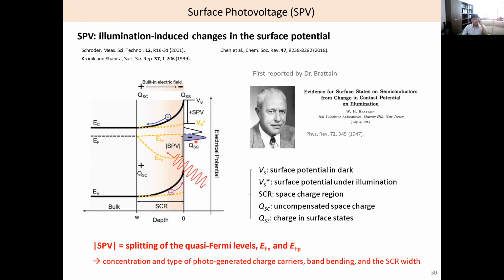Okay. Then we draw the Fermi level of electrons like this here. But what about when we now illuminate light? Light excites electrons from the valence band to the conduction band. So here, maybe you haven't seen this kind of notation. This is the transient electron Fermi level, and this is the transient hole Fermi level. Because we have more electrons and more holes, the electron Fermi level is a little bit higher. So this band is flattened a little bit. And this shorter distance means we have more electrons, right? By this light illumination. And then with more holes, we have this hole Fermi level. And these electrons, by this built-in potential, will be disappearing. So we have this flat band.